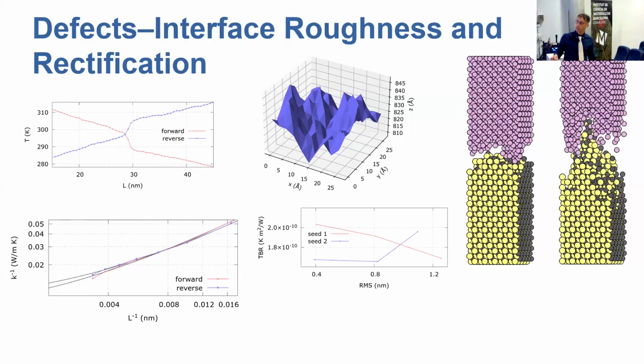And what we did is compute the rectification coefficient, which is basically given by the percentage difference in thermal conductivity in the forward and reverse conditions. We computed these thermal conductivities so we could extract the rectification coefficient for different junction lengths. Why? Because the longer the junction becomes, the less the thermal boundary resistance affects the rectification coefficient, which becomes solely determined by the difference in thermal conductivities between gallium arsenide and germanium.